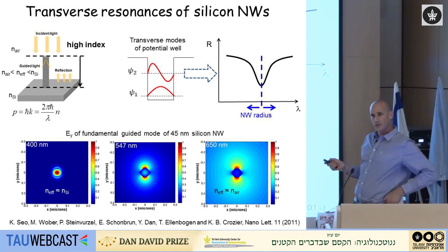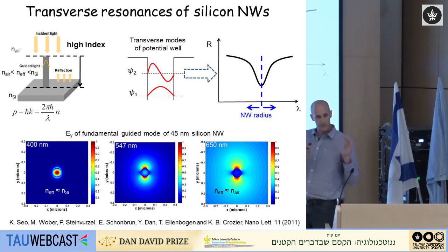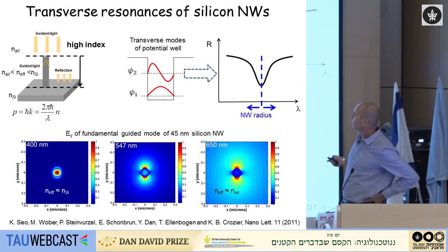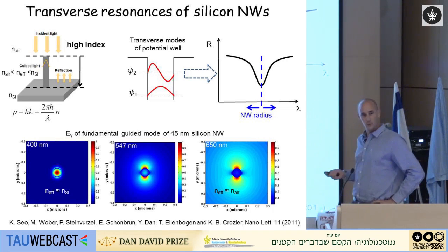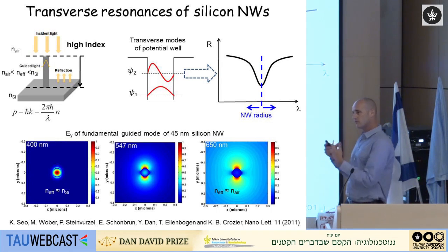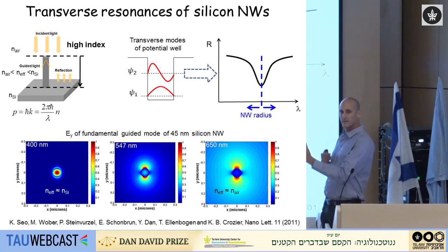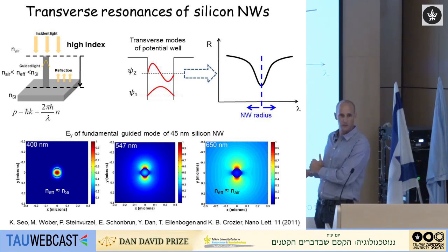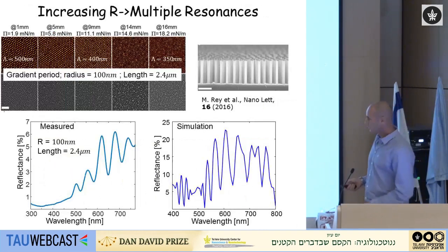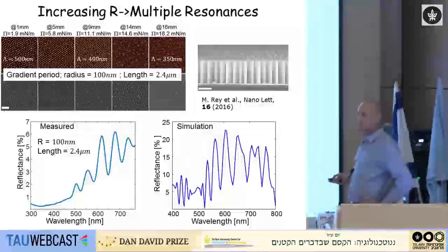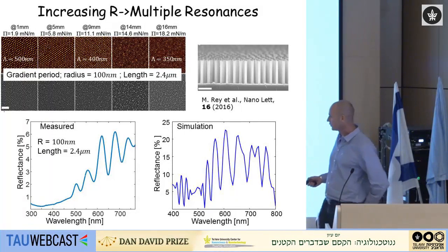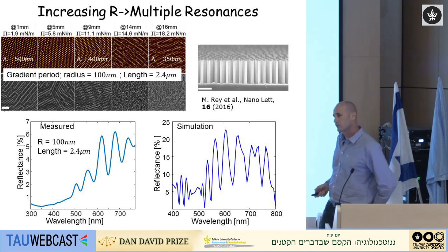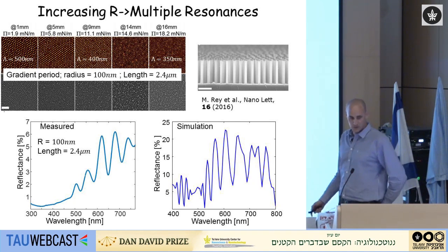You would assume that if we increase the radius of the nanowire from 70 nanometers to 100 nanometers, we will see another dip in reflection due to a higher-order mode. But these systems are full and very rich with physics — you have coupling effects, and small changes take you to a different physical regime. If you change the radius from 70 to 100 nanometers, instead of a broad dip, we see a very sharp oscillating figure in the reflection spectra.